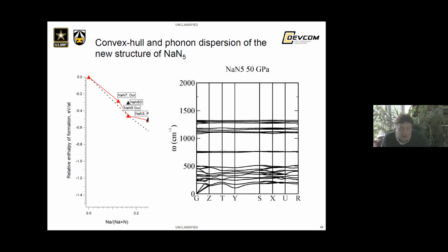We calculated both structures with the same potentials and functionals and found that the new structure of NaN5 with Pmn21 symmetry group has a lower enthalpy. If we use the result in convex hull construction, then the new structure outruns the structure with Cm symmetry group. And this is the previously found structure. Phonon density calculations of the new structure indicate that it's dynamically stable.